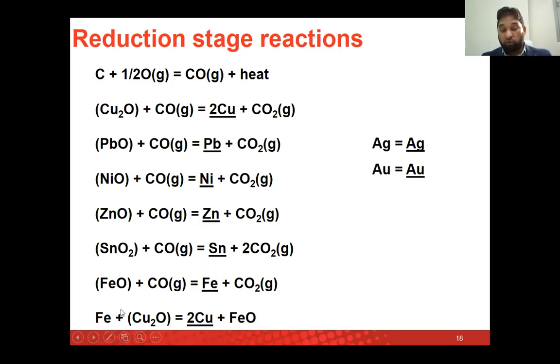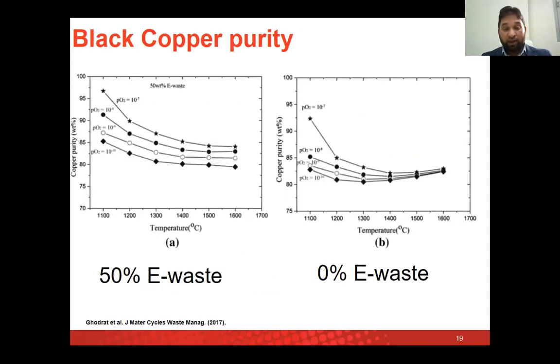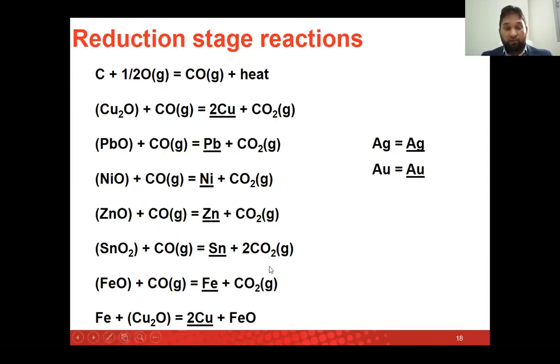And there is also a possible reaction that you have a copper oxide, and then copper oxide will also be reduced with iron to make the copper. So my point is, during the reduction stage, all oxides are reduced with carbon monoxide and they come into the solution phase, okay? But the gold and silver, they were present in printed circuit boards. They will become a part of now copper in as a solution.